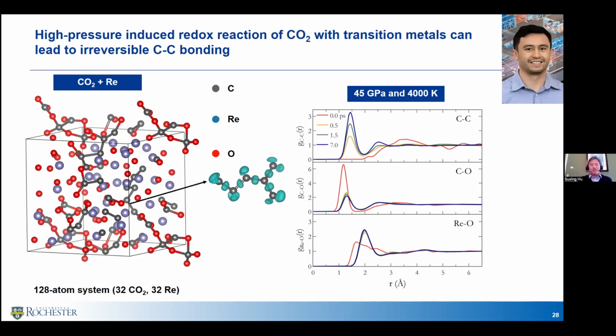The first example Dalen did is adding some rhenium atoms into the system. The surprise he saw is that when you have such a transition metal in the system, the QMD simulation indeed shows that CO2 gets decomposed. So what's the signature?